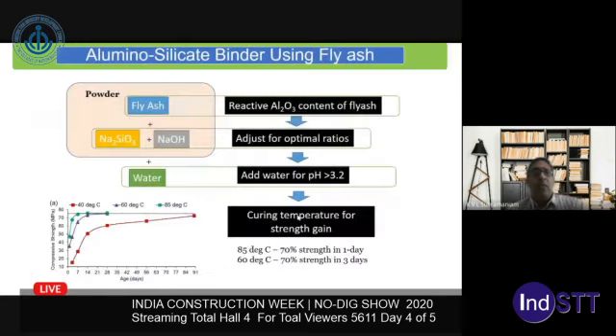So now, what we did is understand the chemistry of the fly ash. We developed a process where, using this low reactive fly ash, which is predominantly available in India, by optimizing the chemistry, by determining the reactive oxide contents, and by optimizing how much activator needs to go in, and activators are primarily provided in the form of sodium silicate and sodium hydroxide, understanding the role of these in the entire reaction chemistry, we've been able to produce geopolymers which consistently give us strengths of about 80 megapascal.